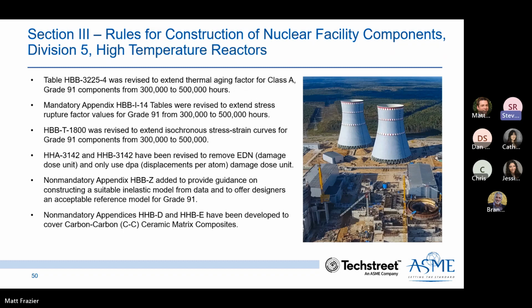In Section 3, Division 5, Table HBB-3225-4 was revised to extend the thermal aging factor for Class A grade 91 components from 300,000 to 500,000 hours. Mandatory Appendix HBB I-14 tables were revised to extend stress rupture factor values for grade 91 from 300,000 to 500,000 hours. HBB T-1800 was revised to extend isochronous stress strain curves for grade 91 components from 300,000 to 500,000.